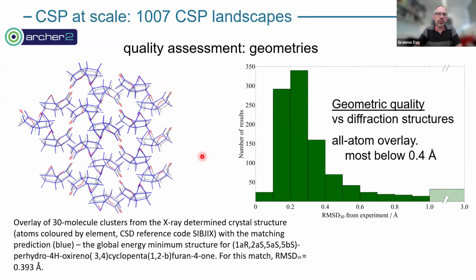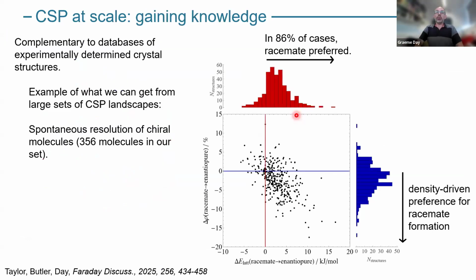And to give you an idea visually of what roughly a 0.4 angstrom RMSD difference looks like, in blue here is a predicted structure for this molecule, and in gray and red is the experimental structure, and that's got an RMSD of 0.39. That's giving you a visual idea of where most of these structures sit in terms of how well geometrically we're reproducing things. So now we think we have a nice database that we've been working on increasing the size of, but just looking at what we've got from 1,000 molecules, we can dig into this and start to see what questions we can answer.